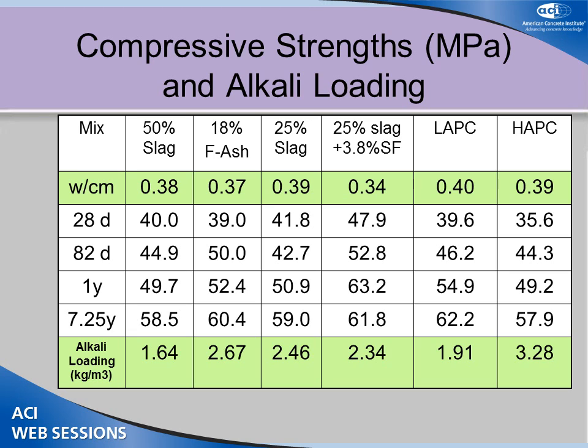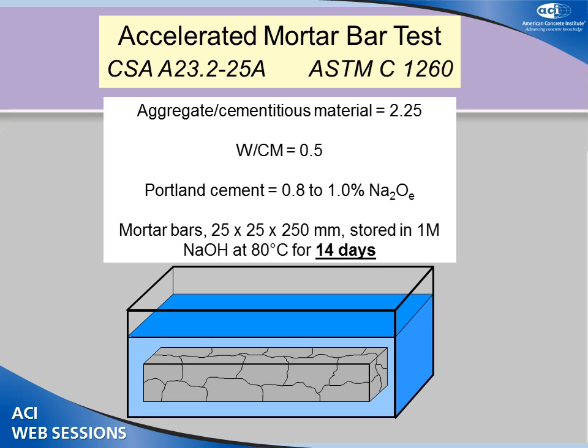The alkali loadings are there. We didn't dope any sodium hydroxide into the blocks. We used the alkalis as they were. So the alkali loadings in kilograms per cubic meter are shown there. We did accelerated mortar bar testing. We did concrete prism testing. Then we've been monitoring the blocks and the pavements.